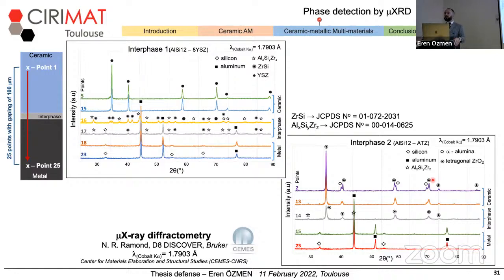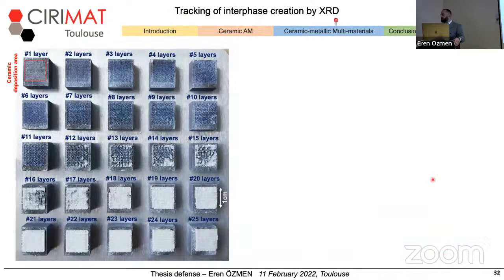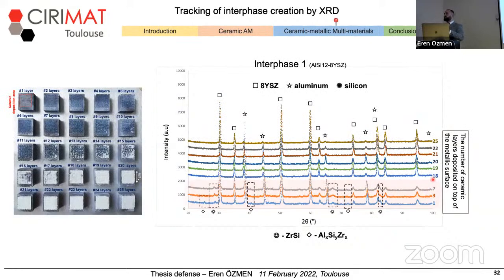To answer that, I ran an experimental procedure where I deposit 1 to 25 layers of ceramics on metallic substrates, and then I take XRD patterns of each sample from the top surface. Then I stack these XRD patterns on top of each other, and from the first layer to 25 layers, I follow the changes in the XRD pattern.